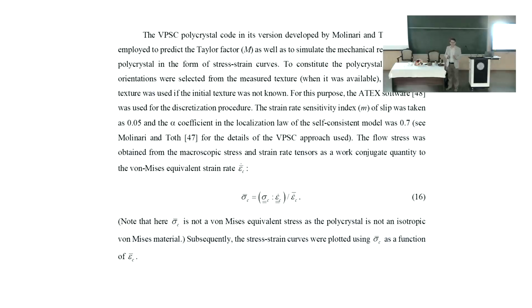Now, for the strain, there is a common agreement. It's not a big problem. We use an equivalent strain, which is an invariant quantity, the von Mises strain. It's the second invariant of the strain tensor, or we usually use the equivalent von Mises strain rate. It's again the second invariant of the strain rate tensor. In any reference system, if you change it, it is the same value. It's very comfortable. There's a common agreement on this. This is a suitable strain measure.